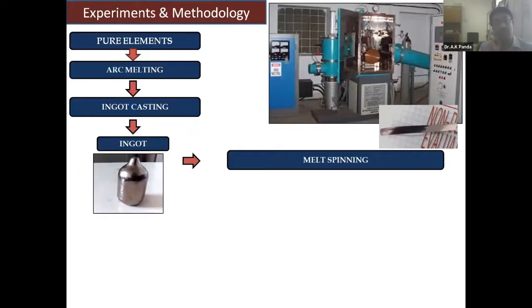Now I move to some of the techniques that we follow in our laboratory. Whenever we take any material, we start off with the pure elements. We go for arc melting and ingot casting, essentially in an inert atmosphere. Typically we make bullet-type ingots, which look shining. But let me make it very clear that working with manganese is not very easy, because if it is electrolytic grade, we have evolution of a lot of gases and a lot of porosity, so we have to work very carefully with it.